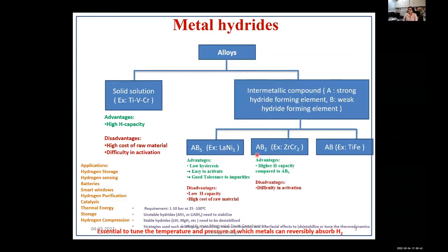Then there are materials like AB2 type of hydrides, zirconium chromium 2, that have the advantage of a higher capacity compared to the first class, AB5. But then the problem is that they are difficult to activate. Activate means the first time when you are putting in hydrogen, there is a lot of resistance. So there is an activation barrier that you have to cross, and that could be by subjecting it to high temperatures or pressures.